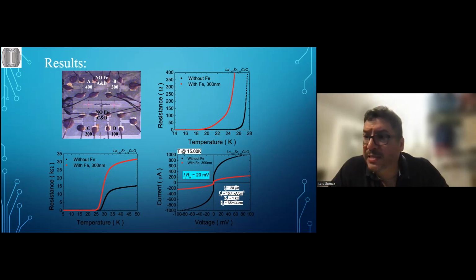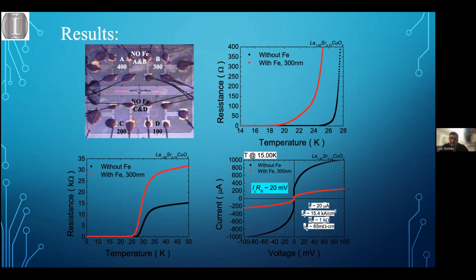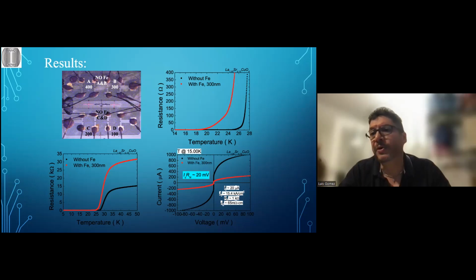Some people talk about that type of thing. I'm not completely convinced that this is the case, but what I can see experimentally is that I have a high resistance value. If I measure the resistivity at this point of the curve and multiply it by the current, that gives me about 20 millivolts. Then I use the other equation, and this actually will be 10 terahertz. That would be the characteristic oscillating frequency of this system, if this is a Josephson junction system. That is the part where I have not completed this research to really prove that this is the case. It is not easy to get a 10 terahertz source.